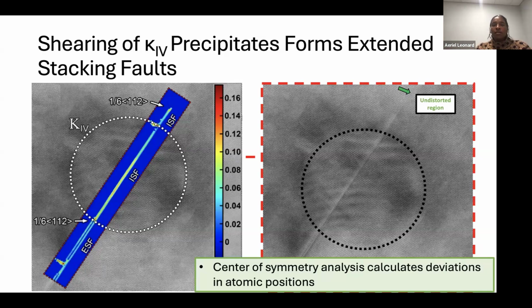So by performing this center of symmetry analysis, what we learned is that we have a full dislocation that's separated into two partials. It's not hard to believe. This is a copper-based alloy. And the leading partial shears through the precipitate, leaving behind an intrinsic stacking fault. What we know from looking at samples at higher plastic strains is that the trailing partial stays behind. So it's almost stuck, pinned at the interface here. And as we'll see in later images, they actually never recombine. So the stacking fault stays in the material.